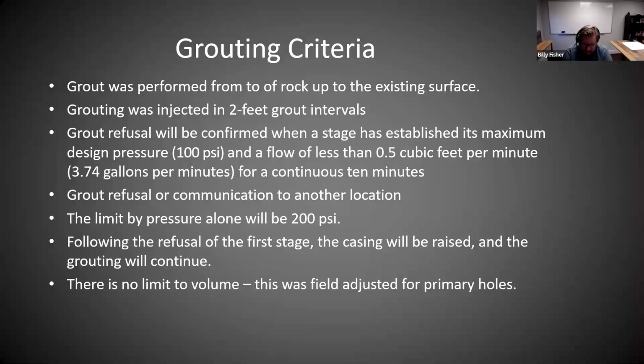Once we were going with the initial primaries, we made a change in the field. We set a volume cutoff just on the outside primaries of like 75 gallons per zone, so that we could try to limit how far the grout was traveling outside of the zone we were trying to grout. So we set volume criteria on just the outer rows, and didn't on the inner rows ultimately. That's when I was talking about needing a flexible grouting program.